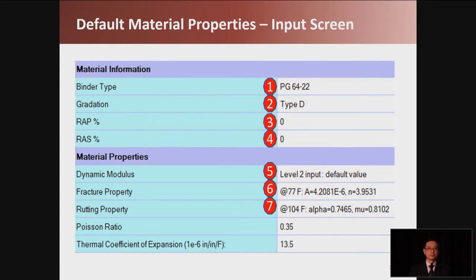So here we show the input screen for the material property. Users only need to choose the binder, the PG grade, and the gradation, like Type D, Type C, and the RAP content and the RAS content. Then the dynamic modulus, the fracture properties, and the rutting properties will be automatically displayed in these items. Of course, if users have the lab test data, they can input this. They can modify these values. But here we provided this default value system, so that will make the program much more convenient to use. It's not realistic to expect the users always have all complete detailed information.